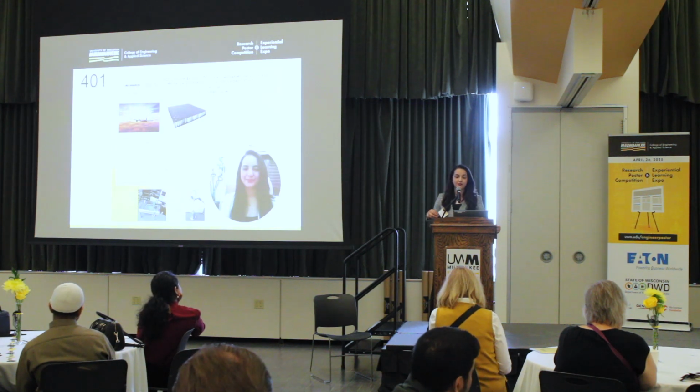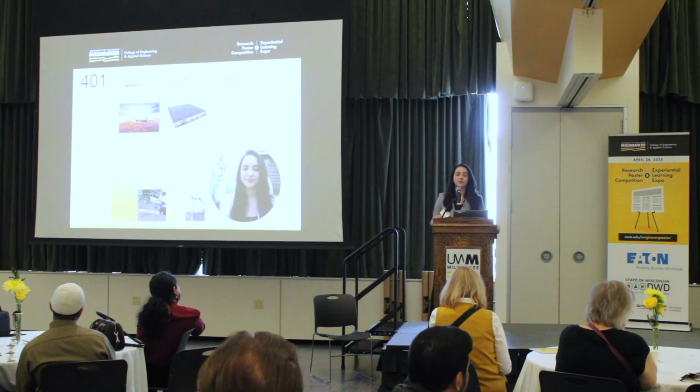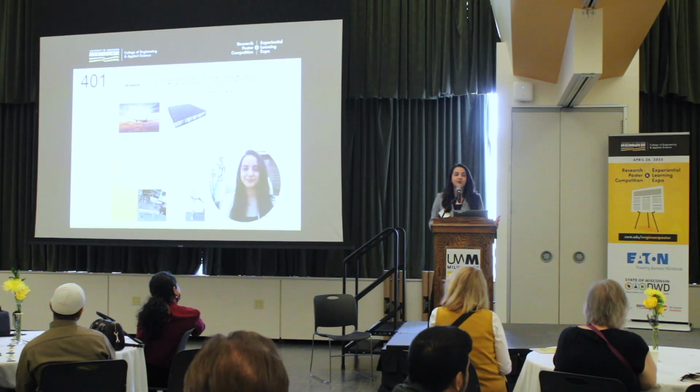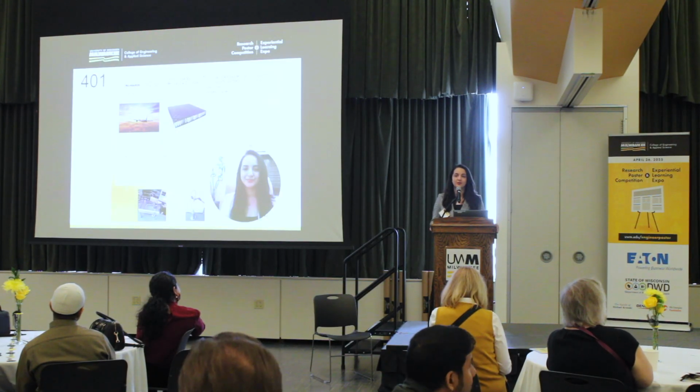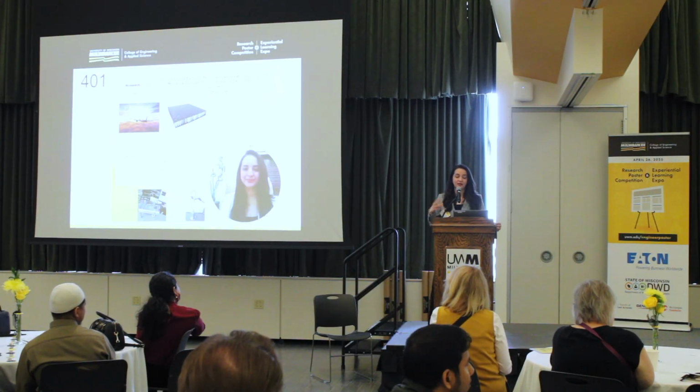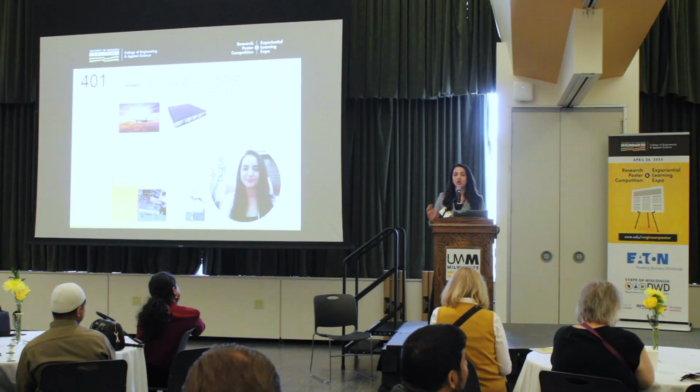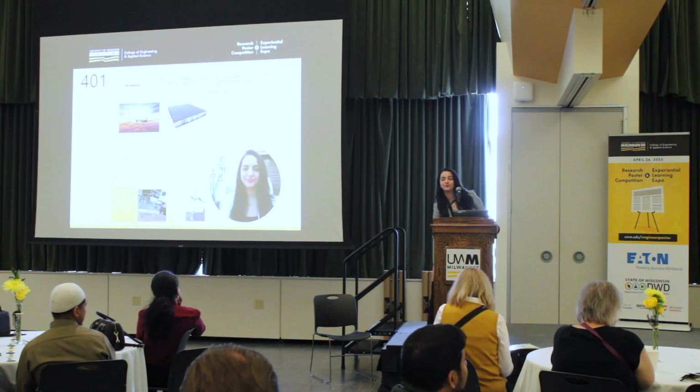Each and every peak in that frequency plot shown over there represents a vibrational response. The height, width, and position of the peak tell us a lot. What I found in control samples was a nice sharp peak, meaning a strong intact sample. However, in compromised or defective samples that have core splices and gaps, the peaks were broader, shorter, and moved in position, and in some cases it was disastrous, where the gap is, there was a huge stiffness degradation.